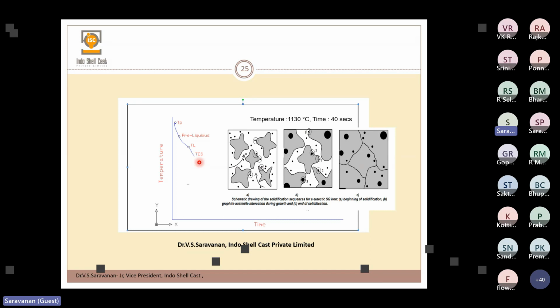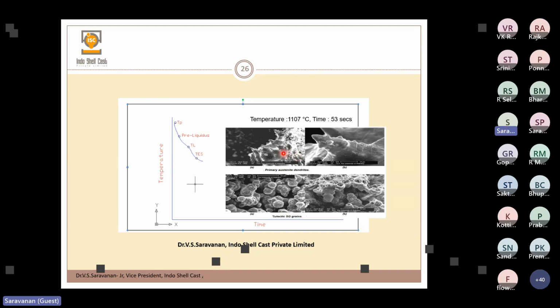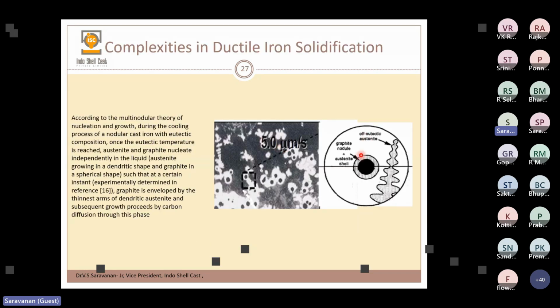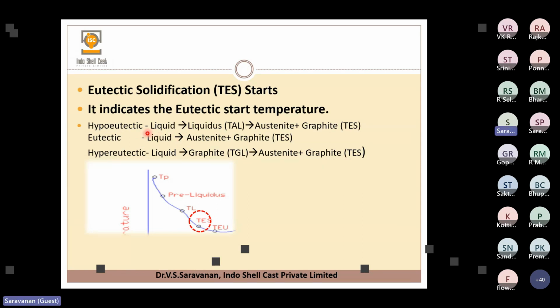Two solid phases. So the austenite will start growing like this in dendrites, and in between the dendrites, graphite will start precipitating and it will come down inside. It will settle inside the nucleation. This is dendrites, so this is the nucleation austenite cell. Once the graphite starts precipitating, again the austenite will form over this graphite also. So on one side it is growing like this, and on the other side over the graphite it is forming like this. So in all areas it starts precipitating. So this is the hypoeutectic.